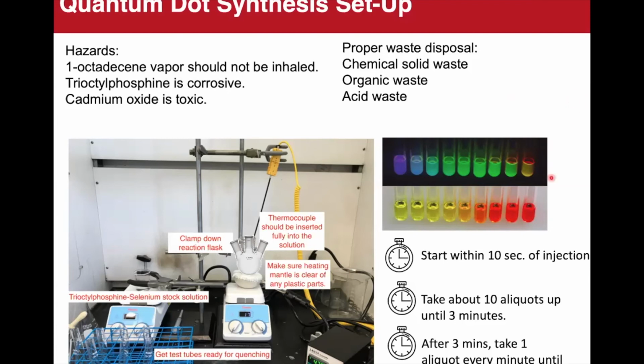synthesis. And so first you'll start off with an injection of the selenium stock solution that will be provided. And within 10 seconds of the injection, you'll need to take out an aliquot, or a small portion of the overall solution that is in the reaction vessel. And there will be test tubes for you to deposit your aliquots